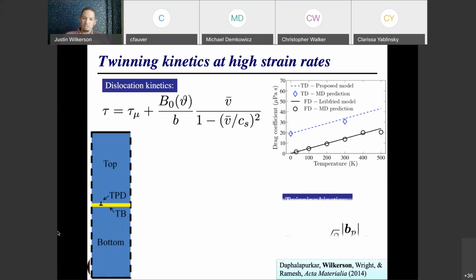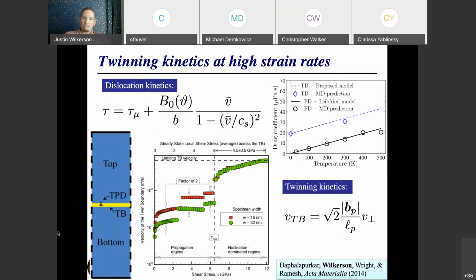And so we did some MD calculations and found that that exactly works. That idea works until you apply so much stress that you're nucleating new twinning partial dislocations. Then that idea kind of falls apart at that point. That's going to be another theme that we're going to talk about later, is that the spacing of defects and the evolution of the spacing of defects is one of the more difficult things to capture in these physics-based frameworks.